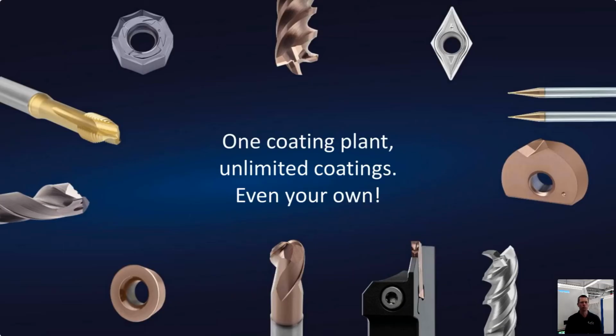And this brings us to a very important point today. The world is extremely unsecure, and it's very difficult to predict something. The most important thing today is flexibility. And with a HiPIMS coater, you can do any cutting tool, whether it's a micro cutter, what you see on the upper right-hand side, whether it's a tap tool, where you don't want to have any droplets in the cutting edges, or you can do a 12 micron thick coating on a heavy-duty insert. Everything in one device, just by changing the recipe. So your investment is future-proof.